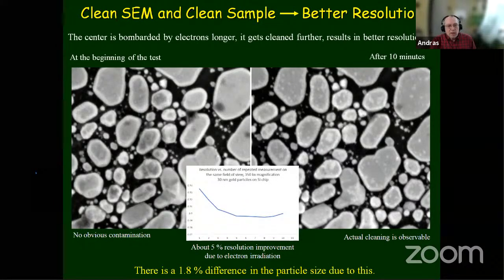So what you see here is the center portion of the same image. It's a digital magnification to show things better. This is evidence that electron irradiation can improve the contamination situation. You can see that the center portion that got irradiated at about 40 times the dose of the usual 1 minute image, small features started to show better. And if you go back to the earlier image, the very first one, you will see some of them, but not many of them.